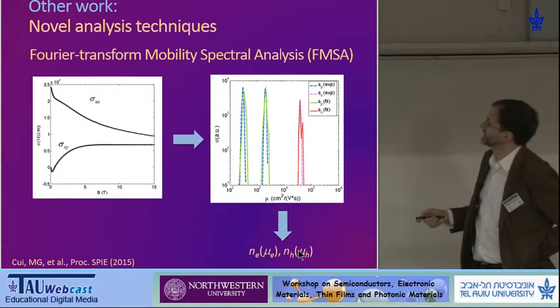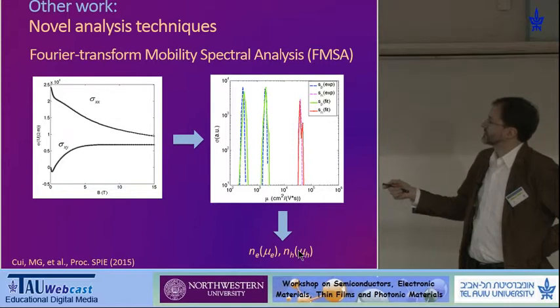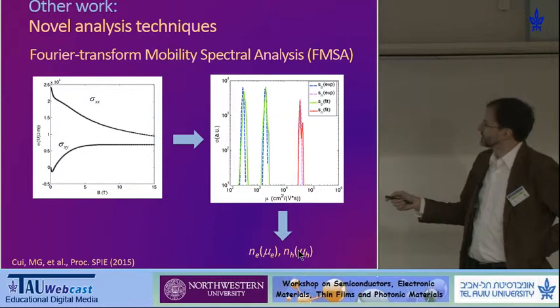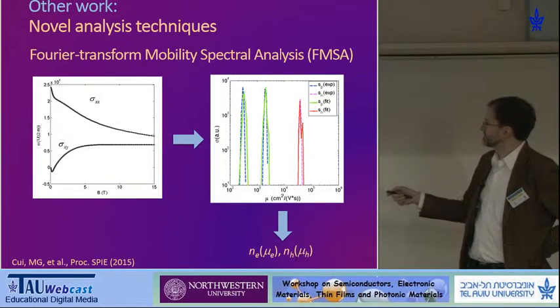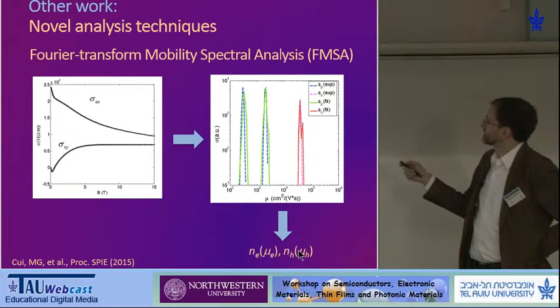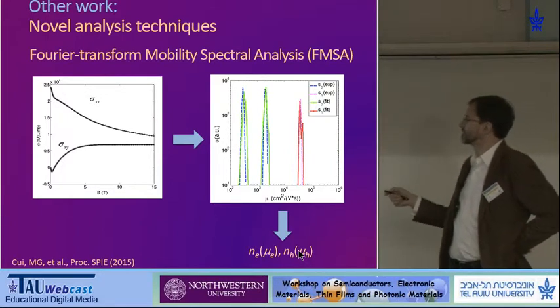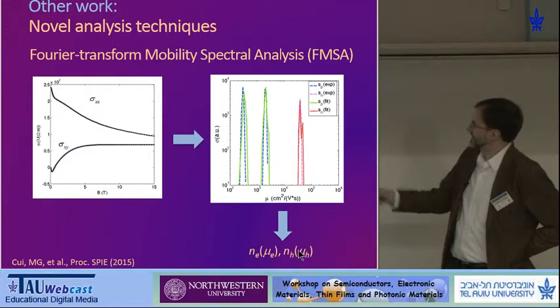Another recent work: if you have a so-called Van der Pauw sample and you do two measurements — measuring the resistivity in the X and Y directions — sometimes you see asymmetries in the resistance versus magnetic field response. We've developed a characterization method that allows us to deduce the density gradient of such a sample. We also have a novel analysis technique where measuring longitudinal and transverse resistance in a magnetic field lets you convert that into a mobility spectrum — conductivity as a function of mobility — showing, for example, two p-type species with low mobility and a single n-type species with high mobility.